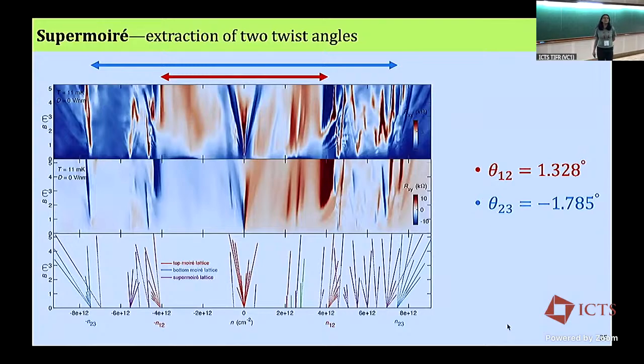But my main point is that these samples are so inhomogeneous at times, and students are making them with their hands. So I don't want to pinpoint something here or there. If we dig enough in twisted trilayer graphene, we see superconductivity everywhere. All the samples, you can see superconductivity. It's just that we don't pursue all of them after maybe 2 or 3 days. That's the reason.